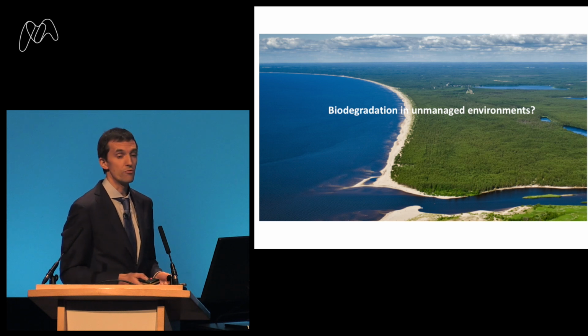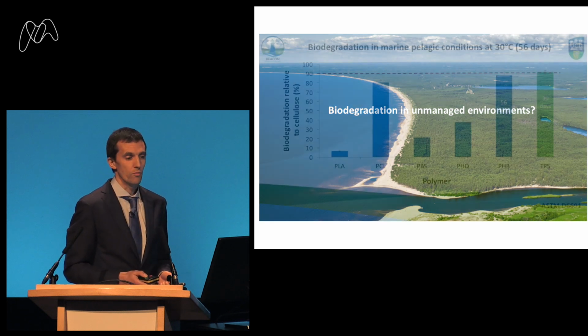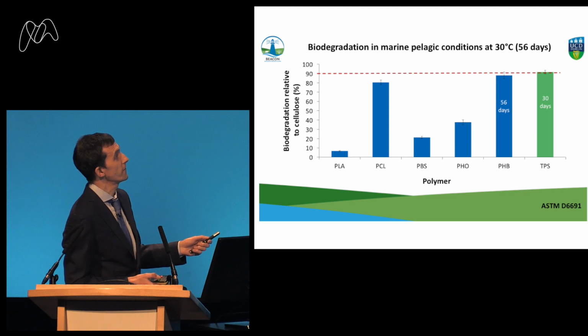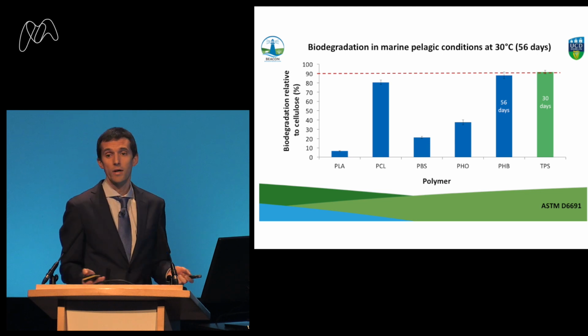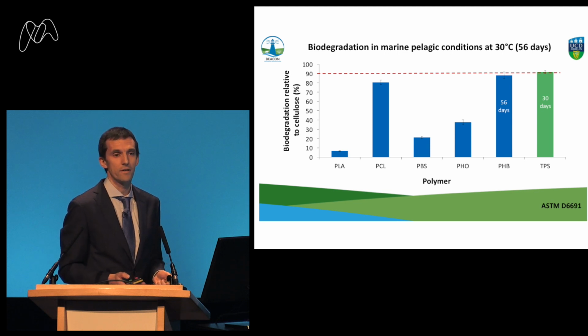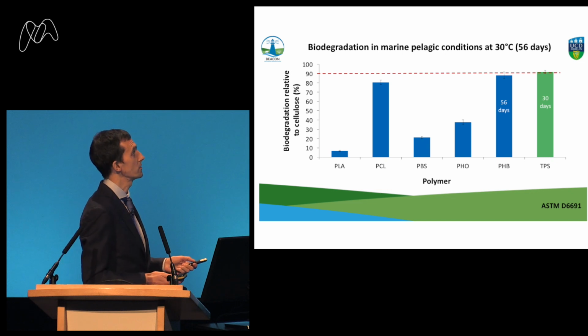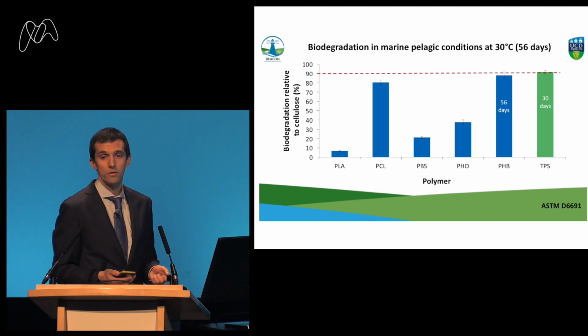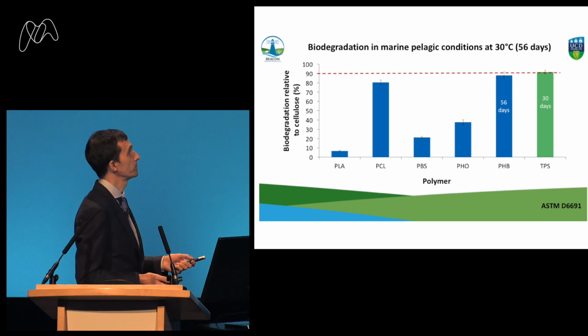So, for example, in the marine, we looked at 30 degrees centigrade and 56 days. That is the standard. And you might argue that in the marine, you're never going to see 30 degrees. But this is the international standard for measuring biodegradation in the marine. They use a 30 degree standard, and they use seawater that has a natural microbial flora.